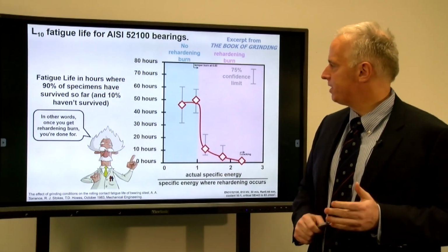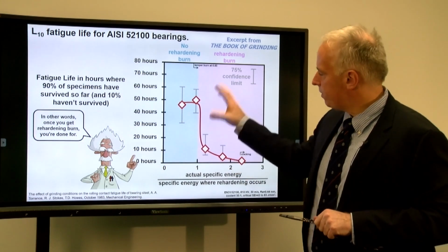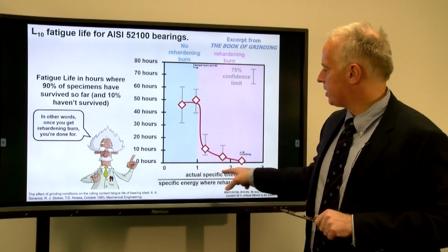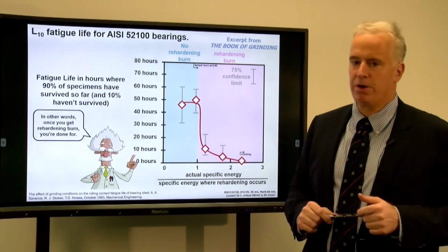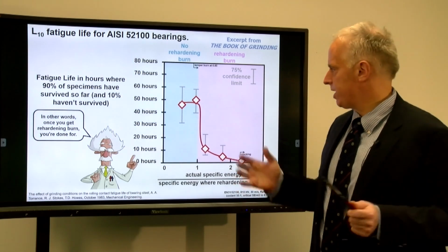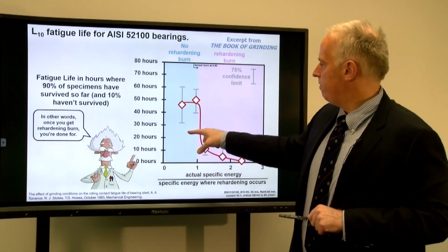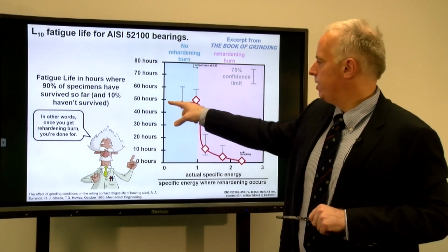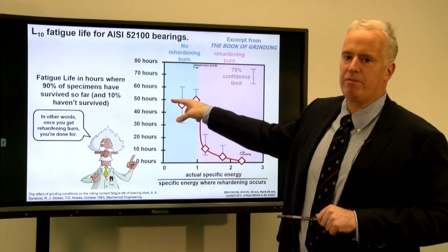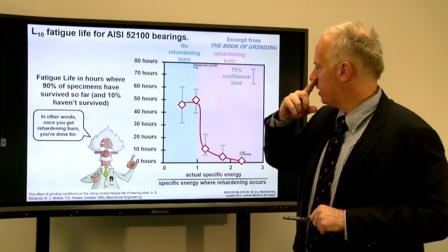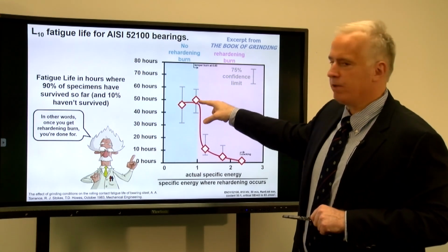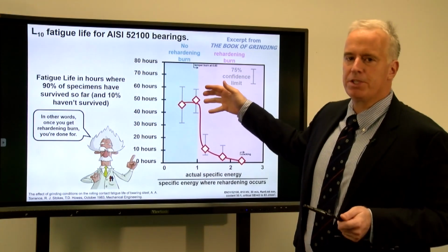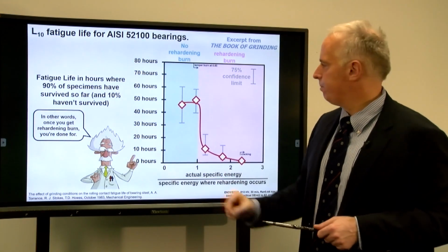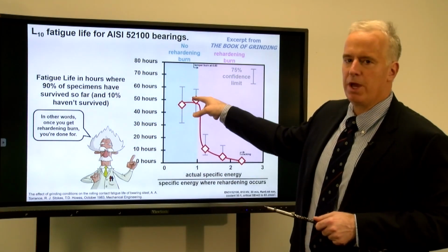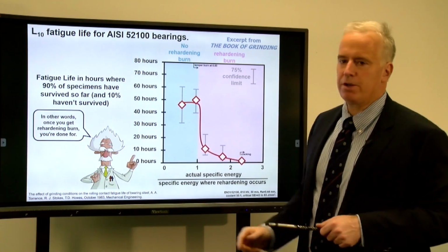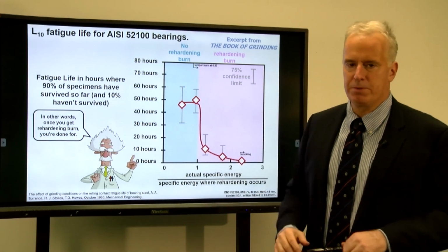So here we have what Dr. T did. And what he found, this gets a little tricky about the way he did it, is the specific energy where rehardening burn occurs. You could argue it's just kind of temperature. If you don't have rehardening burn, you're going to get 45 hours of fatigue life before the thing breaks. If you're right on the edge of rehardening burn, probably a little bit of residual tensile stress, but not rehardening burn yet, you're still doing okay. But as soon as you get rehardening burn, everything goes bad.